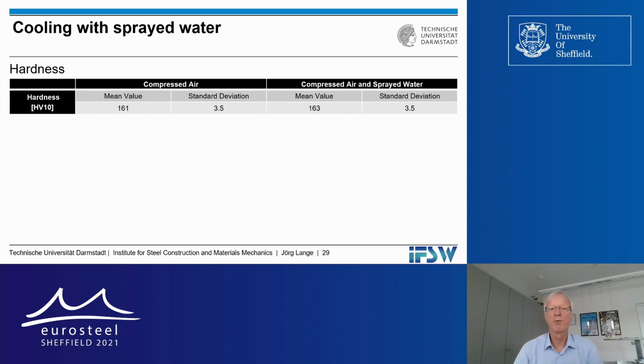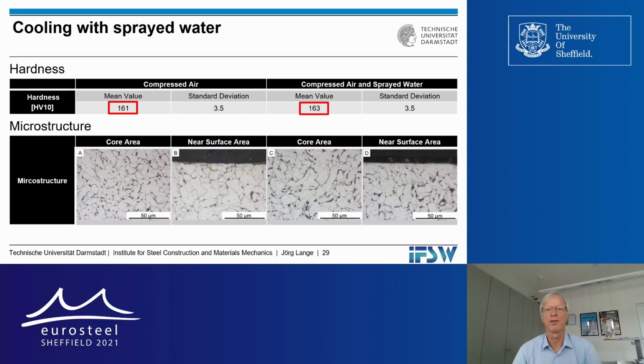We tried to improve the cooling with sprayed water, not only compressed air. And you see that compressed air and sprayed water had no significant influence on the hardness. We have a hardness of 161 to 163, and also the microstructure is very similar. So the cooling with sprayed water improved the production time, reduced it, but had no negative influence on the material characteristics.